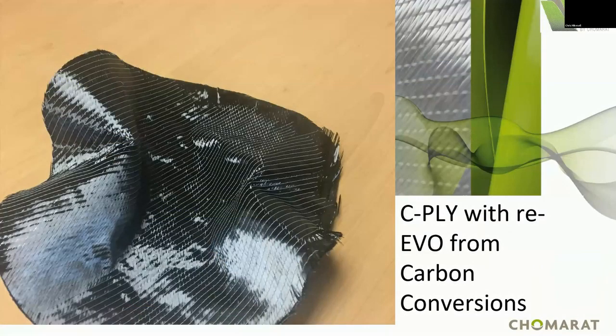Here's a combination product we did with Carbon Conversions where we took a recycled carbon fiber mat material. We combined it with C-ply, hoping to take advantage of the recycled material, the conformability of that, and then the very low resin content and continuous fiber of our C-ply. And so combining those materials together, we were able to play around with thermoplastics and thermosets and create kind of a combination product that could be suitable for many applications.